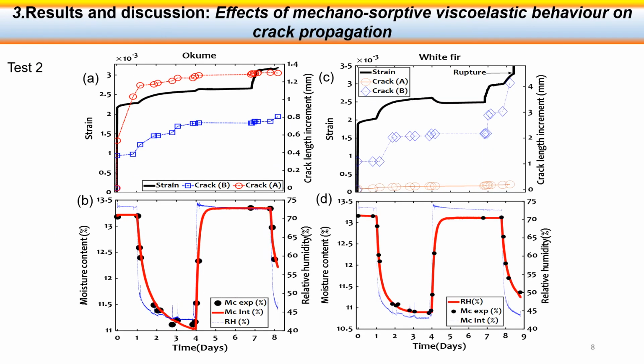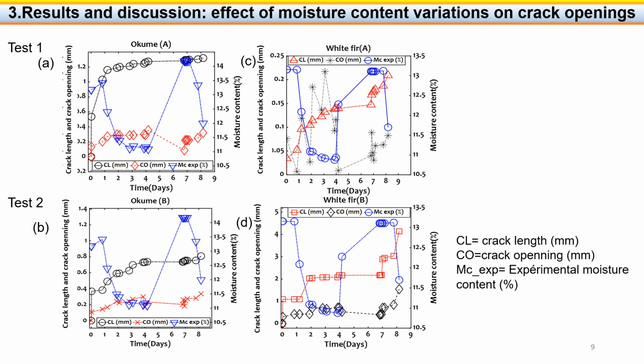The same observation can be seen in this slide, which represents the effect of the sorption cycle on the crack propagation. This figure shows the behavior of the crack opening under the effect of variation of the experimental moisture content of the two phases A and B of the Okume and white fir specimens for test 1 and test 2. The crack opening increases during the drying phase. However, it remains constant or closes during the wetting phase. The increase in crack opening during the humidification phase on day 7 is explained by the additional loading.